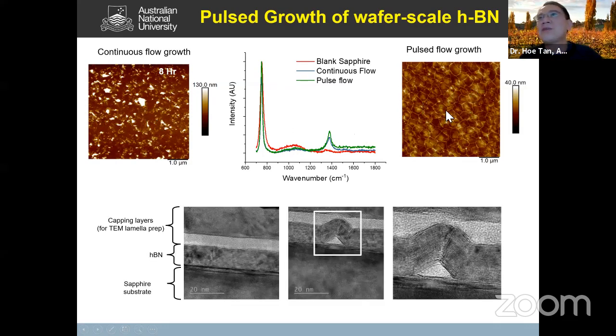I don't know if you can see this very well, but you can see probably there's like domains here. Okay, so these are not crystal domains, they are actually wrinkles. So what happens is we grow this hexagonal boron nitride on sapphire substrate, which grows fine, but the problem happens when we start to cool down and take it out from the growth chamber. And because of the mismatch in the thermal expansion coefficient between HBN and sapphire, the film starts to wrinkle, okay?